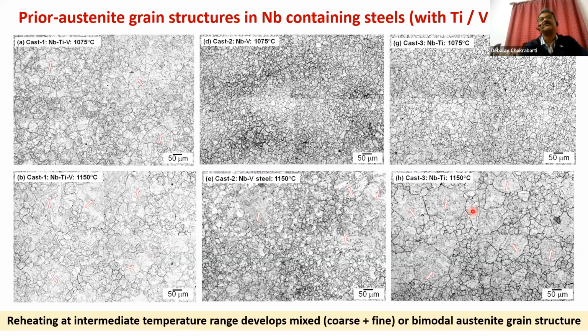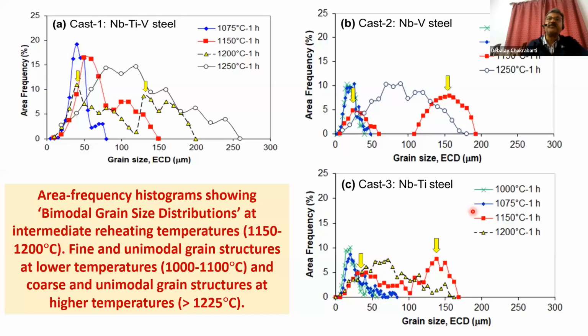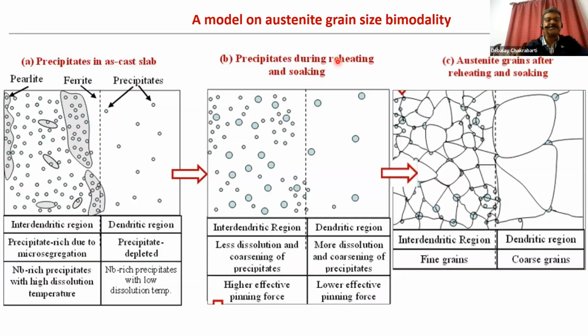And this non-uniform grain structure, after rolling, can result in this kind of grain size variation, which is one of the biggest problems for niobium steel. And it creates grain size bimodality. You can see in certain cases, like this red colored grain size distribution plot, y-axis is frequency, x-axis is grain size, it's showing a bimodality, because it means there are fine grains along with coarse grains. And as I said, this coarse grain can be very detrimental to the properties.